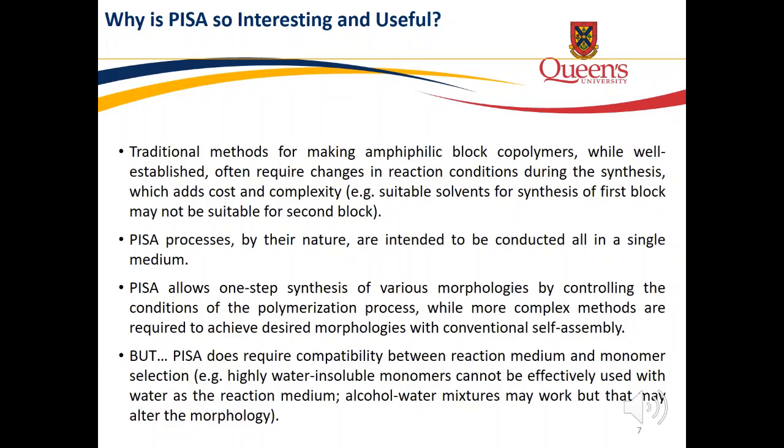So for example, if you have very highly water-insoluble monomers and you're trying to conduct a PISA in an aqueous environment, you may have difficulties getting enough monomer dissolved that you can make the second block. Now, there are ways around that, and one of the most effective routes is to use alcohol-water mixtures or alcohol itself instead of just an aqueous environment.